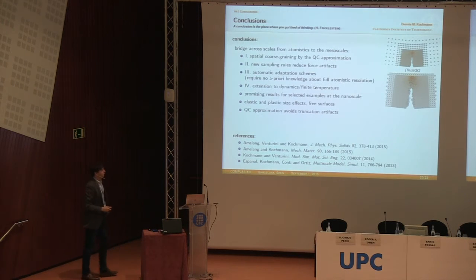perfectly on time. I'd like to conclude that I tried to show you how we can bridge across scales from atomistics to the mesoscales to the continuum. The first step is spatial coarse graining, and we adopted the QC approximation. The second step was to efficiently speed up calculations by using quadrature type rules. The third step was automatic mesh adaptation.